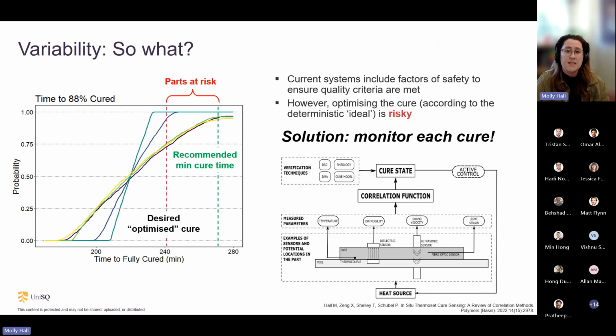Thermocouples are probably the most common. If you stick a thermocouple in the middle of the part, you can measure the temperature profile that that specific part is experiencing, pop that into your simulation, and predict how well cured the part is. However, for flyaway aerospace applications, unfortunately, we can't go fly with the thermocouple hanging out of our parts. So we need a technique that's non-invasive.